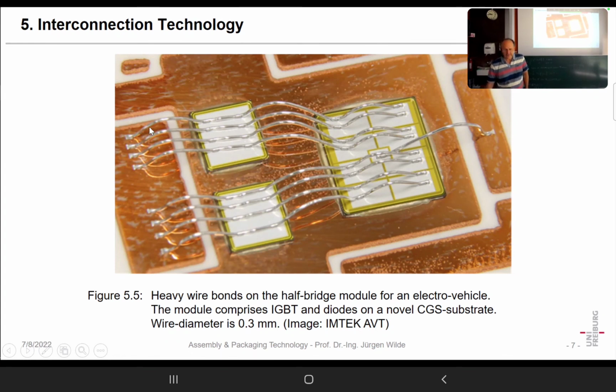A disadvantage of wedge bonding is that you can only have very small angular variations. With ball bonding, from the first bond, because it's symmetric, you can go in every direction. Yeah, the whole system is symmetric. That's not the case here. The initial direction of your wire must be kept. You have small variations because the diodes are more apart than, let's say, the size of the chip. So it works a little, but not too much, because otherwise you would have too strong deformations here. But that's a good example of heavy wire bonding.